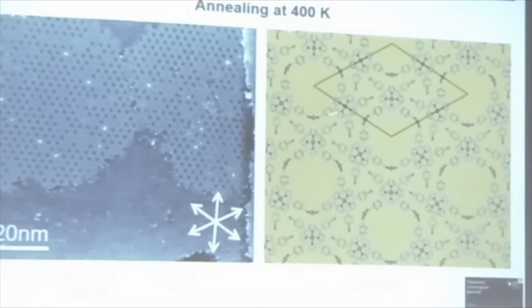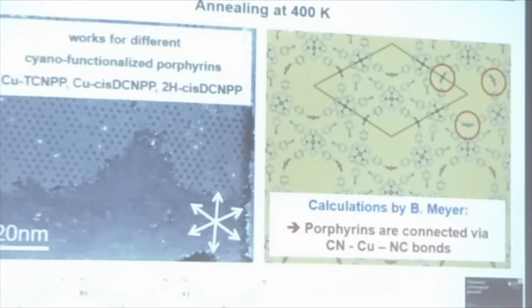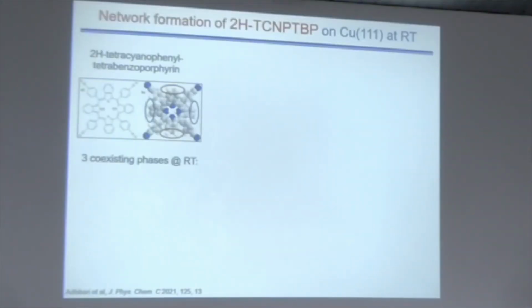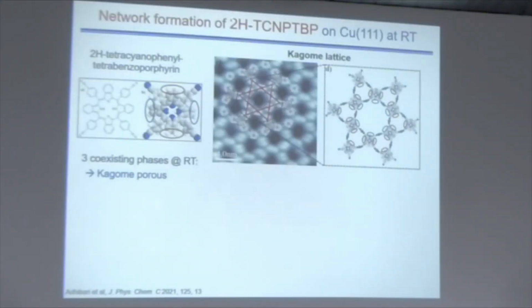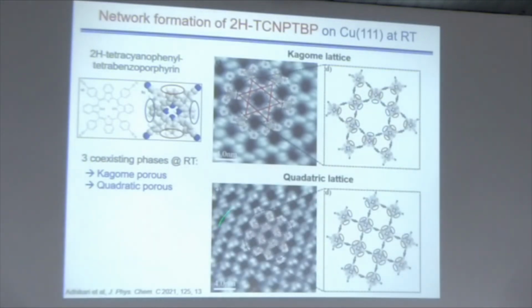And these copper adatoms are the driving force for the formation of all these ordered structures. I don't want to go into the detail here because I have a short last chapter. You also find it on other porphyrins, here with benzo groups. On copper, you find really beautiful Kagome lattices or quadratic lattices. These are coexisting structures on the surface, and it's always the cyano groups connected via copper atoms.